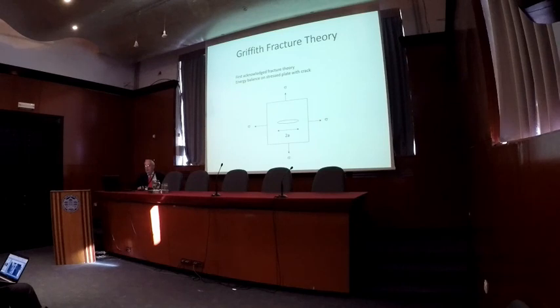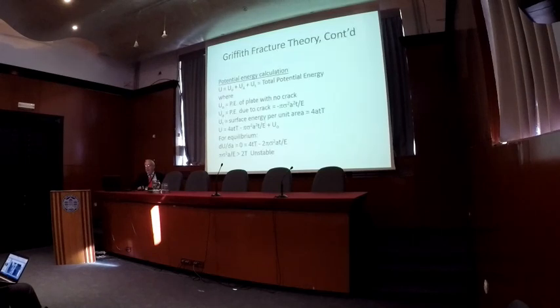But the Griffith idea was this: he took a plate, two-dimensional, with a defect of size 2a. It's kind of an infinite plate, but it's loaded biaxially with stresses sigma, and for that plate he considered the contributions to the potential energy. There were three contributions. One is the plate with no crack in it at all. The second is the potential energy caused by introducing a crack. That was the Inglis solution from way back when. And the third one is the surface energy that's created during the formation of the cracks.